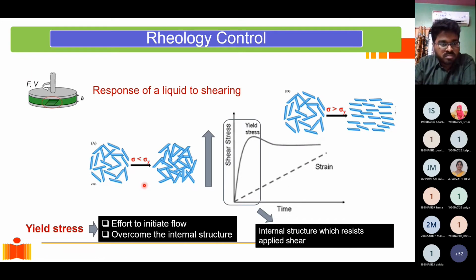When I have a material at rest and I start shearing it, initially the particles are in a randomly distributed state. When I start shearing, these particles tend to cluster up and offer more and more resistance to shear. So the shear resistance actually increases when I start applying shear. Eventually the network ruptures, and all the particles get aligned and start flowing. So the material has some initial resistance and doesn't flow if you just apply some shear stress. That's what we are discovering: if it is sitting at rest, it takes some effort to initiate flow. That effort is called yield stress. It is different from the yield stress we measure for steels and other materials. This is the yield stress of a fluid suspension, the effort it takes to initiate flow, and it has to do with the way the particles inside the material are aligned. Initially, they densify and form a dense network with increased resistance to flow.